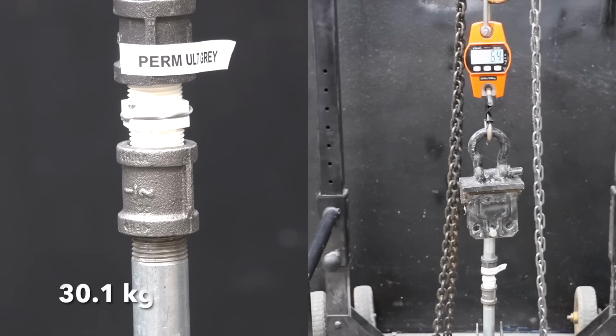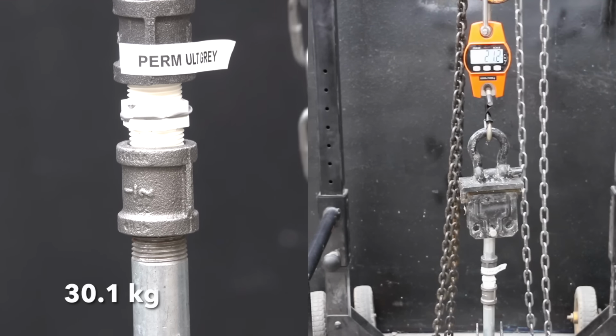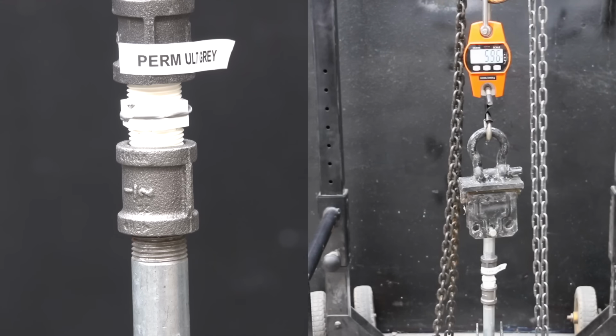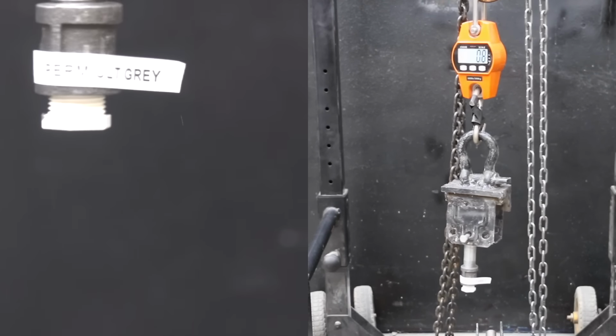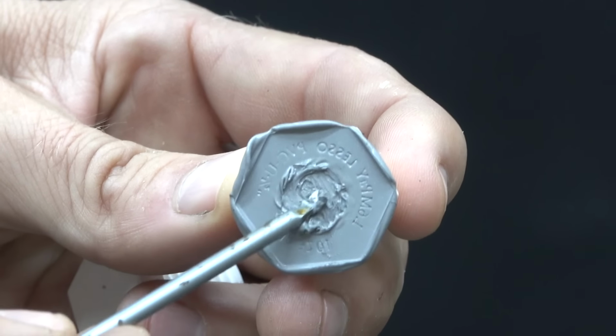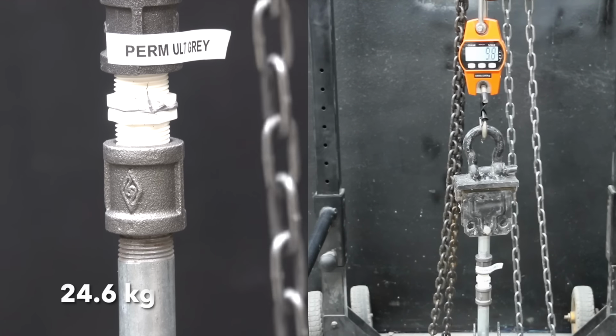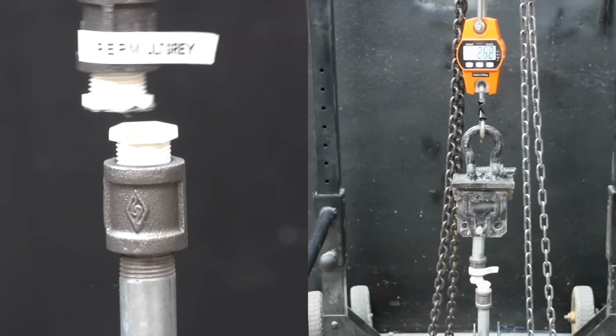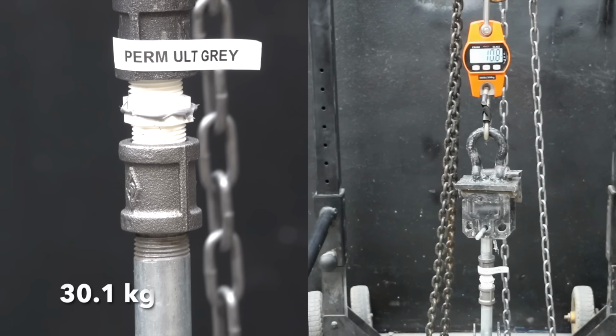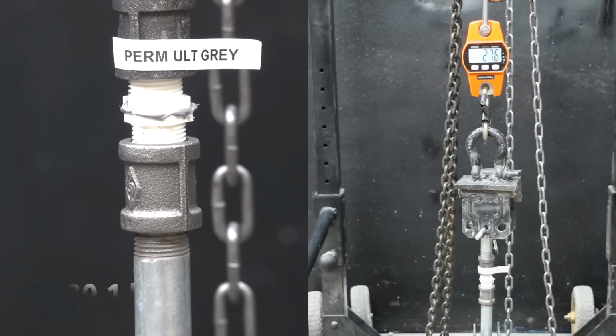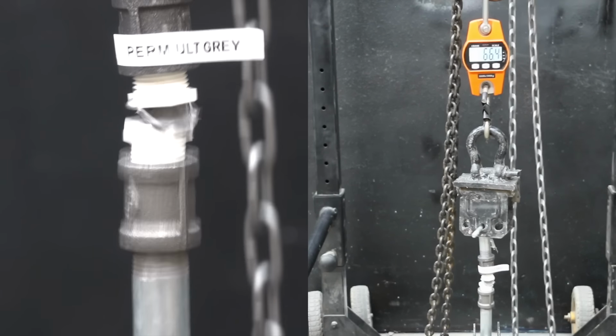Let's test the tensile strength first. And the Permatex Ultra Grey came apart at 66.4 pounds on the first test piece. Even after 72 hours, there's an area in the center of the PVC end cap that's not yet cured. The width of the cured area is 5.79 millimeters. And the second piece didn't do quite as well as the first one at 54.2 pounds. And the third test piece performed almost the same as the first at 66.4 pounds. So pretty consistent results for the Permatex.